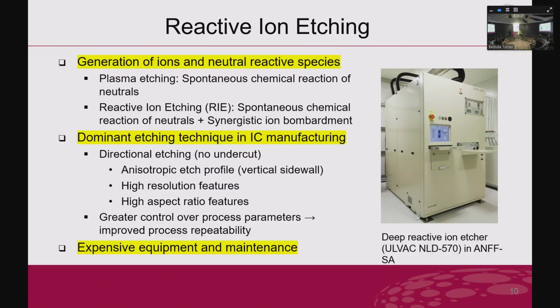And the reason behind that is when you etch different products or substrates, you will have byproducts happen in your chambers. Especially when some metal is involved, it becomes what we call byproduct in your chamber, and then it will affect your etch rate. It turns out at a certain time you need to open the chamber, clean up the chamber, and make sure the efficiency can go back to normal. So that's why we have a regular maintenance schedule for our etching system. It's the same for the chip manufacturer.